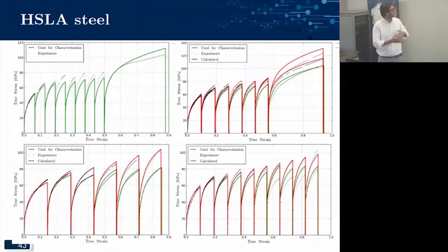So here you can again see tuning the material model so that all its parameters predict the structural response. The green curves I've used within the optimization procedure, and the red curves I've used as a validation step. Without training on them, you can see that some of them do fairly well at predicting what it would look like, despite the fact that it's not seeing that exact history. Despite not seeing the exact deformation curves in the lower bottom, for example, we've come very close to modeling the structural response of the material, considering that temperature and strain rate history.